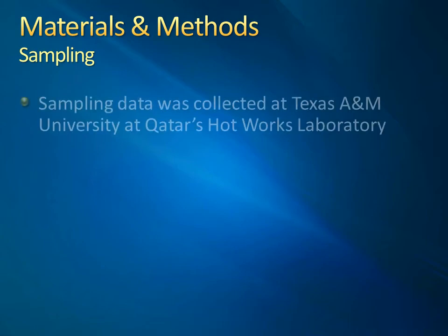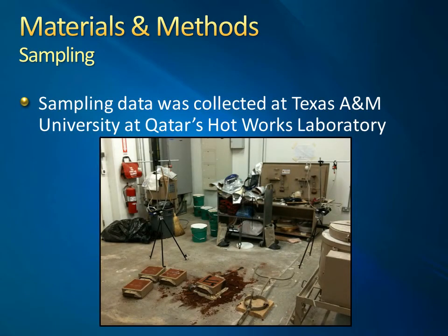Every morning, the sampling pump's flow rates were verified and recorded. After calibration, the sampling apparatuses were attached to stands at a height of 5 feet on the perimeter of the foundry operations to sample the air in the breathing zone. 3 samples for each assay were collected during the foundry operations during an 8-hour period work shift.